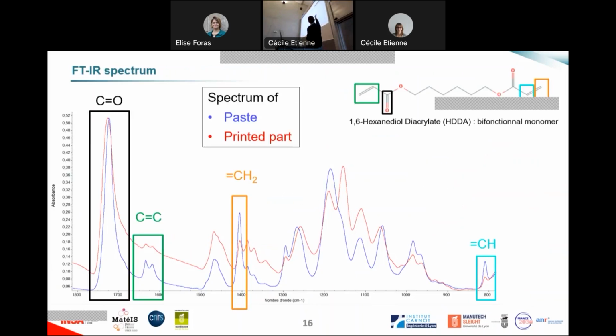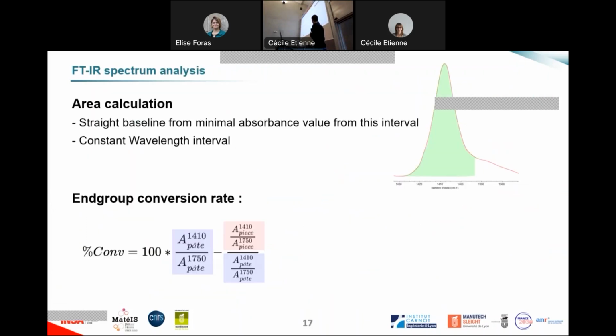Here you can see on my monomer the different species that you can locate on the spectrum. What is very important is the first peak that corresponds to the C=O double bond, which doesn't move when we have polymerization because it's always in the monomer or in the polymer. So this peak won't change, and it will be our reference to see the variation of the heights of the other peaks. These other peaks will change in height because they disappear during polymerization. This way, we will be able to characterize the percentage of conversion of our polymers.